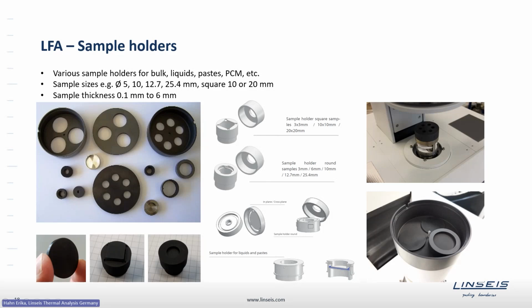So on this slide, you see here the sample robot as well as the different sample holders. The laser flash analyzer generally is designed for solid samples, for bulk materials, more precisely, but you can use it also for liquids or pastes, fiber materials, and so on. So more or less all kind of materials, but you might need a special sample holder for that. So typical sample size is about a 1-inch diameter or a half-inch diameter. Basically, also slightly smaller samples are possible, or one can use also square samples.